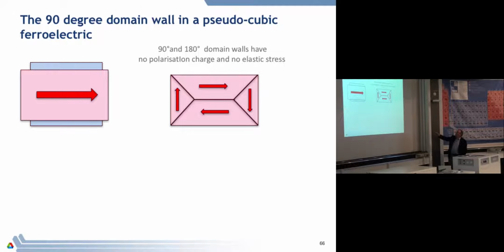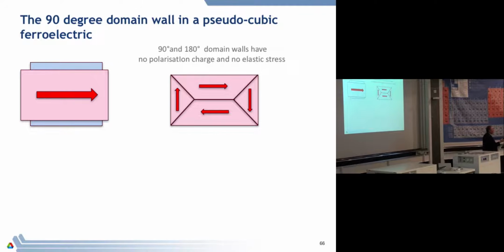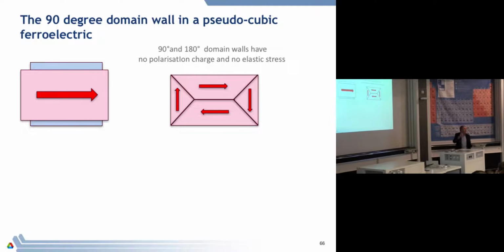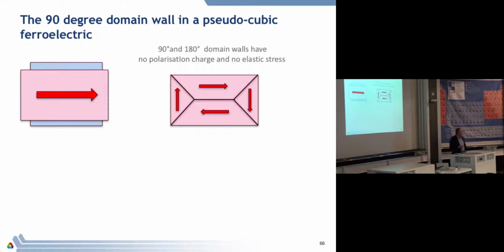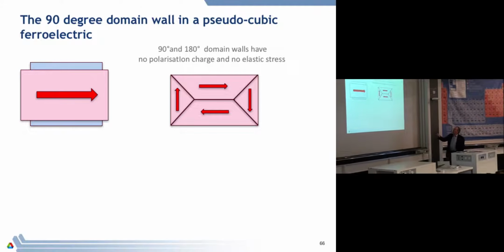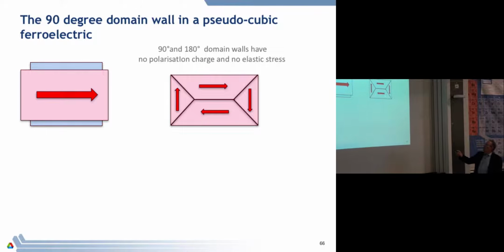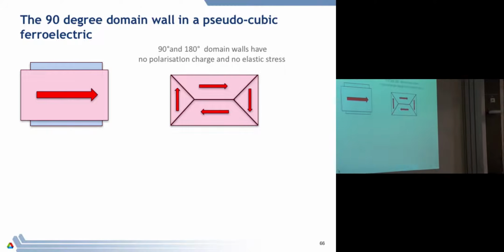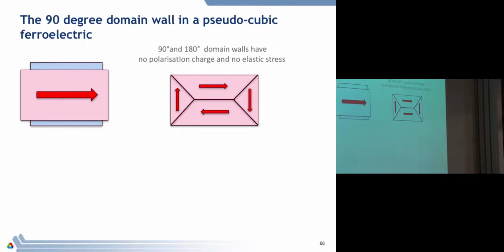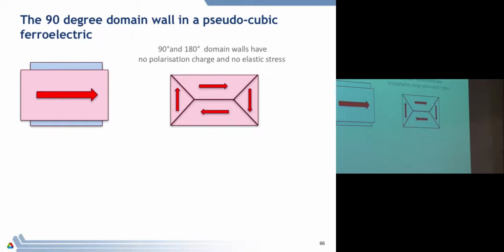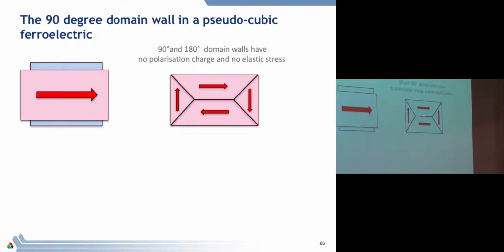So that means that there's no surface charge that develops in this structure. Okay? Unlike the lanthanum aluminate strontium titanate situation where I had head to head, and therefore there was a charge here. So this is neutral. That's kind of low energy. It likes that. The other thing is, if you just think for a while, you'll also realize that this is the only way that I can join the domains together so that the crystal doesn't crack. This line has to be exactly at 45 degrees, or sometimes this is called a 90-degree domain wall, and this is a 180-degree domain wall here. And those are the only 2 stable situations for domain walls that won't produce cracking.